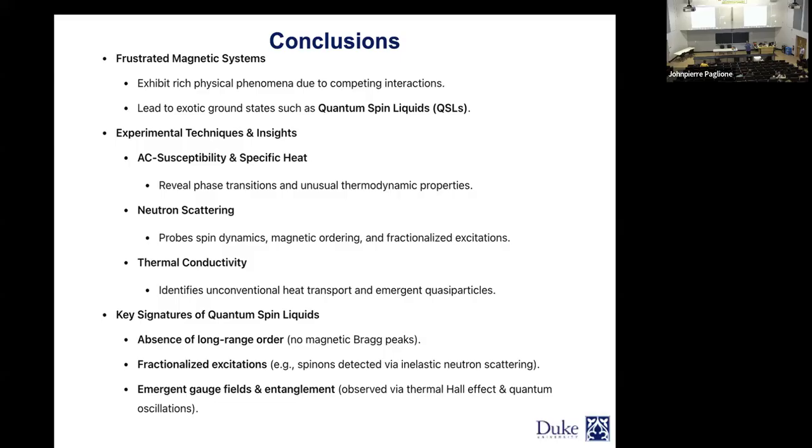No. For a quantum spin liquid, you really don't want to see a lot of that, you want to have a unique relaxation time. And one way to do that, again, is the Cole-Cole plot. If you look at the real and imaginary part of the susceptibility and fit that data, are you going to get alpha close to 0, a unique relaxation time, or are you going to get closer to alpha equal to 1, which is going to be a distribution of the relaxation times? I see. Thank you.